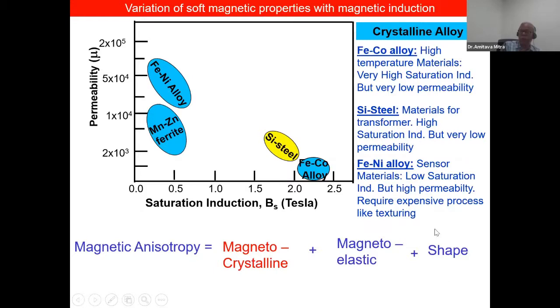And shape anisotropy, basically, you can control by choosing the shape. This is in your control actually. But if we go to the amorphous stage, then this magnetocrystalline anisotropy is not there, because it is amorphous - there is no crystallinity. So due to rapid solidification and going to the amorphous phase, we are reducing the magnetocrystalline anisotropy energy. So the major anisotropy becomes the magnetoelastic and the shape anisotropy.